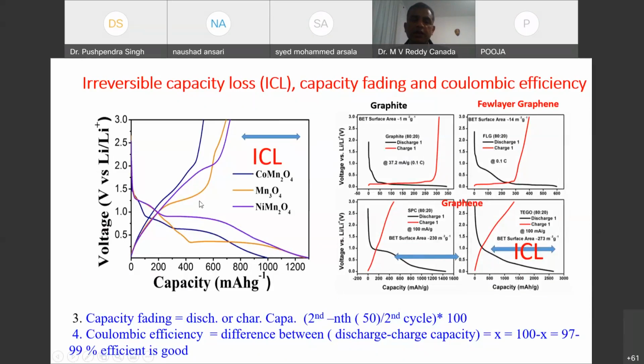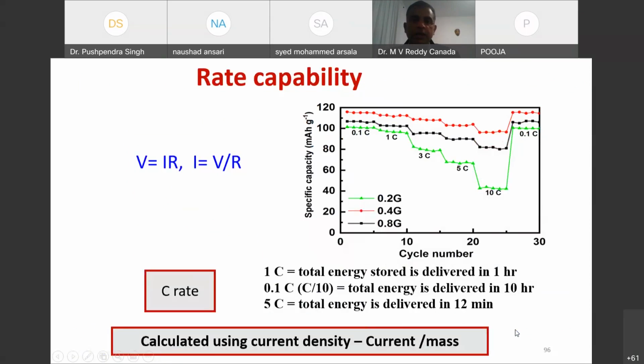Again, you have to get lower capacity fading, meaning the difference between the discharge capacity at the nth cycle, for example, second minus 50th or 5000th or whatever the number, divided by the second cycle. You have to get minimum values. That's how we can tell the capacity fading. Coulombic efficiency is the difference between the discharge and charge, and from there we can calculate the Coulombic efficiency. Rate capability also means, for example, 0.1 C means C divided by 10. You may get some capacity value, and for 5 C, which means 12 minutes, you can see depending on the material, the capacity is going to change.